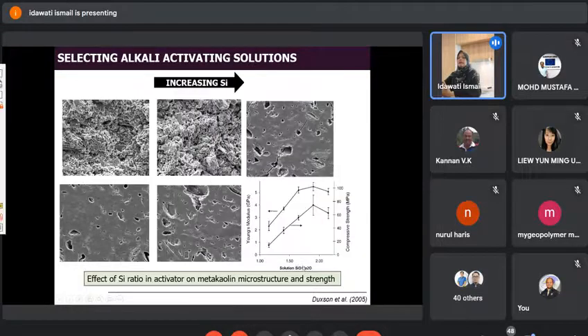You can see that the silicate to sodium solution ratio will affect the compressive strength. And under the microscope, we also see a denser structure when you have a certain amount of silicate. So this is more on controlling the silicate content of your activating solution.